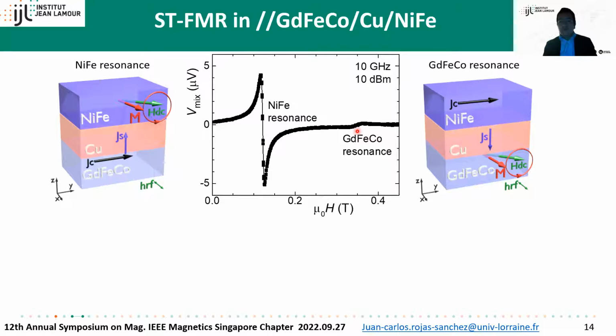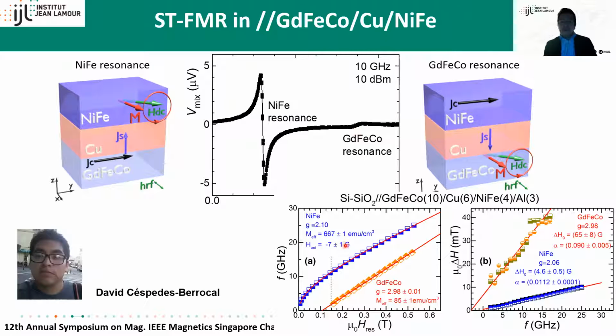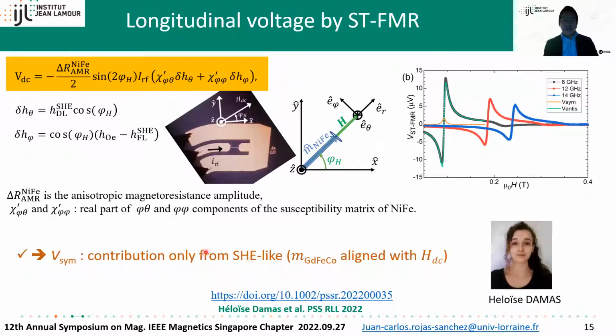We can do frequency dependence to access, for example, the magnetic anisotropy, looking at frequency versus resonant field, or the magnetic damping, looking at the line width versus frequency. So that is ferromagnetic resonance, but beyond that, we want to quantify the charge-spin current conversion in gadolinium iron cobalt. For that, we have to look at the nickel iron resonance, because in this situation the gadolinium iron cobalt will produce an oscillating spin current that affects the magnetization dynamics of permalloy. And in this recent work, this year, we did a more detailed calculation.